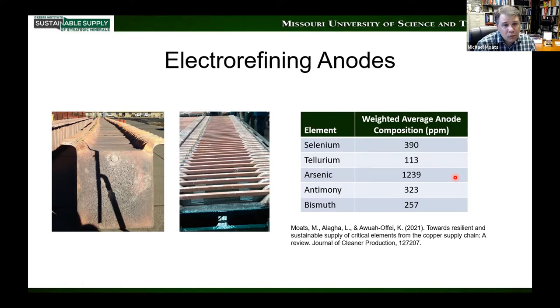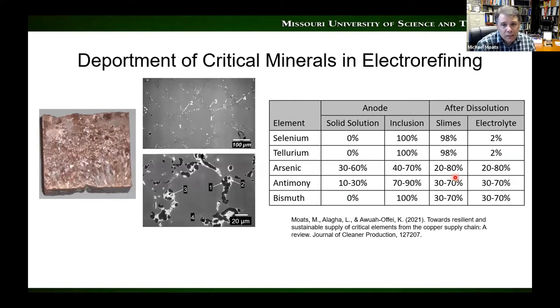So there's a lot more concentration in the anodes. In the anode phase, most of these elements are in little secondary phases. So these are micrographs, and you have a copper grain. A few of the elements are dissolved in the copper, but most are in these inclusions around the grain boundaries. What happens to those inclusions when we go through the process defines whether they're going to end up in slimes, which are solid particles that are left over after dissolving the copper, or they're going to dissolve and go into the electrolyte.